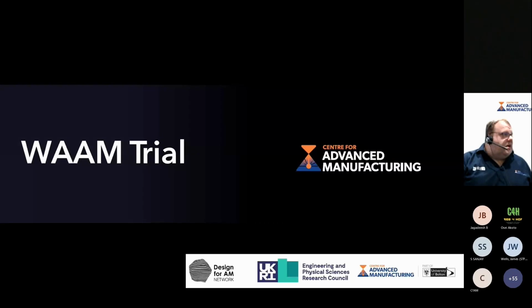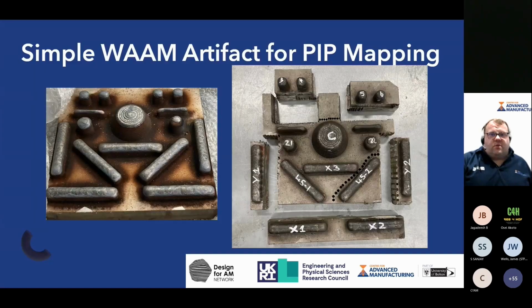The second trial that I'm quickly going to go through is our wire arc additive trial. We looked at a couple of geometries, a couple of angles and shapes, and the idea was that these would be converted into a combination of some PIP coupons as well as some tensile standard ASTM E8 coupons, thin wall, thick wall, different geometries, and we wanted to then do some cut-ups and do some initial trials.